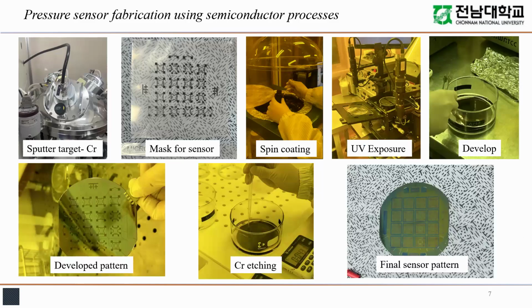And here just shows the real condition of the sensor deposition and the patterning process. First shows the sputter target connection of the chromium, and there is a film mask for the sensor patterns. Then we conduct the photolithography using the AZ JXR PR to make the sensor patterns. First is the spin coating, then UV exposure, and then develop to make the PR pattern as shown at the left bottom side. After that, we will conduct the chrome etching process to make the sensor pattern. And after removing the PR, we will get the final sensor on the surface.